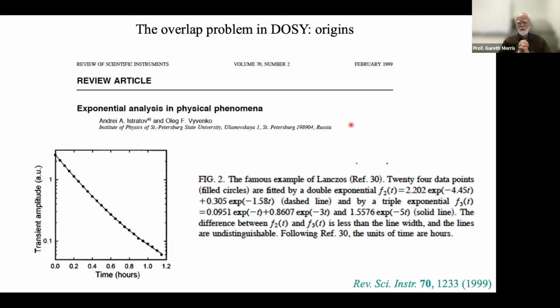If we have two peaks which overlap in an NMR spectrum, and we do diffusion NMR, then that composite signal will decay in a way that depends on both diffusion coefficients. It'll be a bi-exponential decay. And naively, we might say, oh, well, let's just do a bi-exponential fit. As we'll see a little bit later, unfortunately, it ain't that simple. So let's just look at some practical consequences.